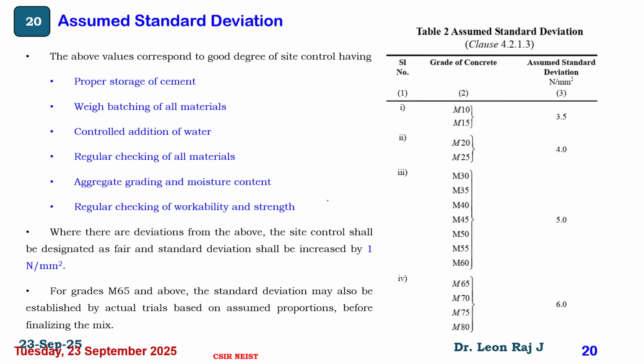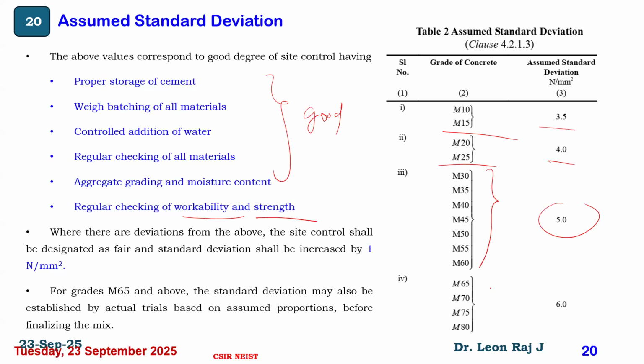Then assumed standard deviation. The conditions to declare a good site condition are proper storage of cement, weigh batching of all materials, controlled addition of water, regular checking of all materials, aggregate grading and moisture content, then regular checking of workability and strength. So for a good site condition, for M10 to M15 the assumed standard deviation is 3.5, M20 to M25 standard deviation is 4, for M30 to M60 standard deviation is 5, and for M65 to M80 the standard deviation is 6.